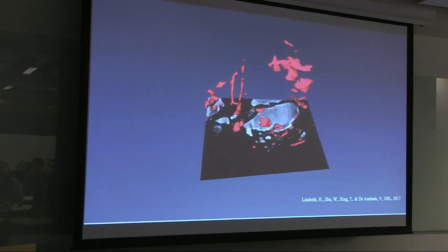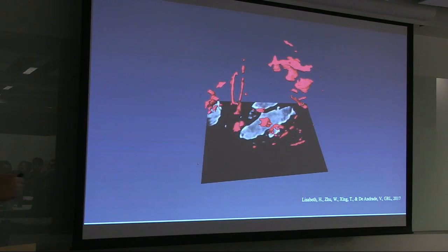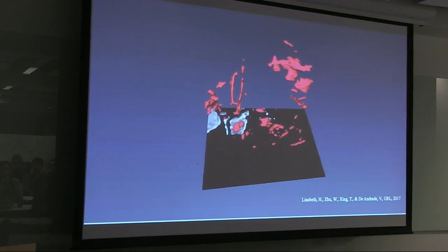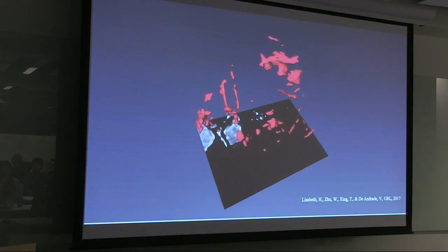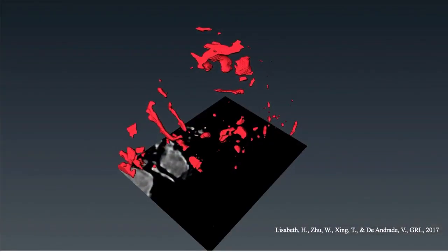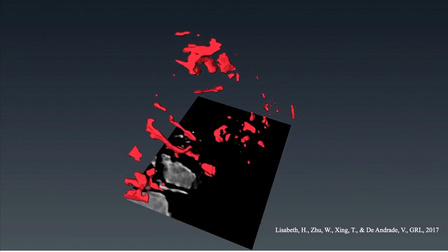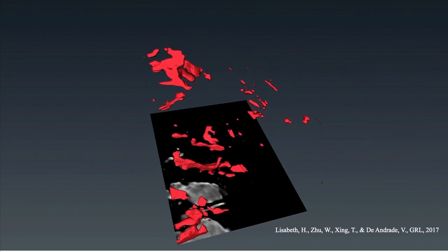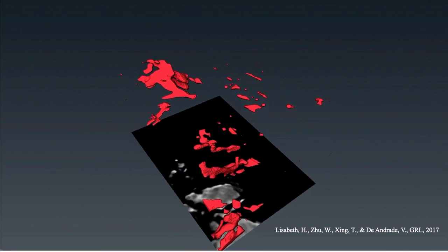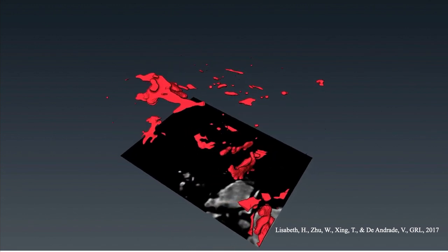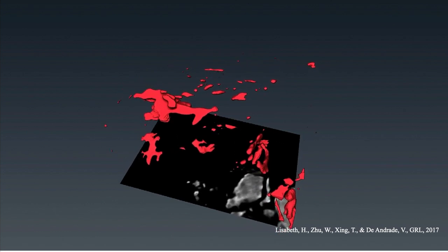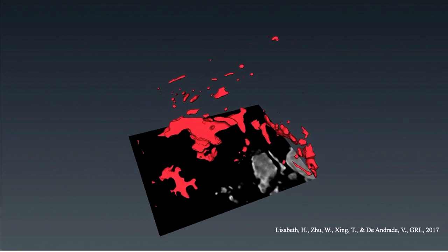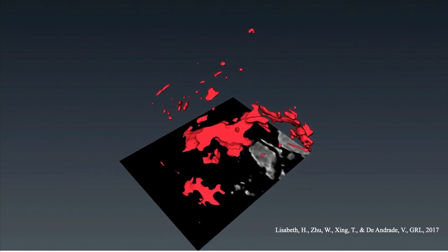And what's the scale there? For the diameter of the tubes, they are about 0.5 micron. So basically, these pore tubes will provide a subsurface dissolution channel that helps maintain the reaction. It can also make the sample more susceptible to later fracture by creating these weak spots through dissolution.